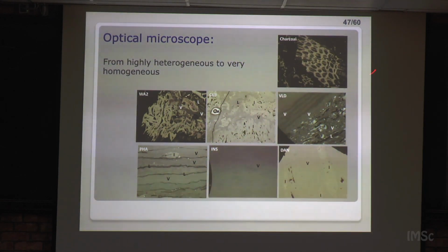And what I just want to point out is that these samples go from highly heterogeneous, you see here, highly heterogeneous with big holes, etc., to much more homogeneous. All this is coal, okay? And this is because of this evolution when being buried, when this material evolves, what they call the rank of the coal. All the different macerals become more and more equal, and you cannot distinguish them anymore. They also lose porosity at the microscale, but gain porosity at the nanoscale. So this somehow is more similar to Vycor, because it's porous at the nanoscale, whereas here it's porous more in the macroscale and highly heterogeneous.